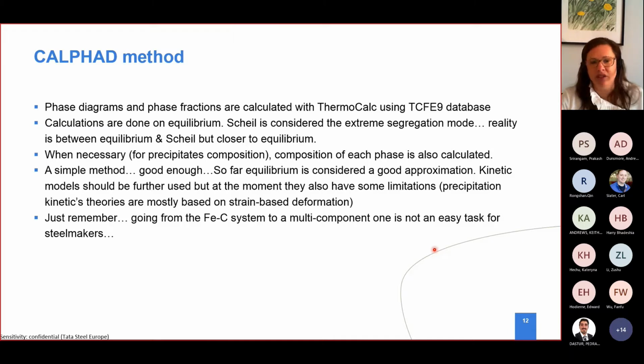But then sometimes you need something that tells you about the precipitation, the precipitate composition for each steel. You could also calculate it with Thermo-Calc or with any thermodynamic program. However, it's a simple method. It is good enough. It's not bad at all. It's much better than a carbon equivalent formula. But you need kinetics. So there are some limitations that you have to be aware of. But just remember, going from a black and white, simplified iron-carbon system to a multi-component system is not easy. And not only to calculate it, but also to understand it, particularly on a daily basis for steelmakers.